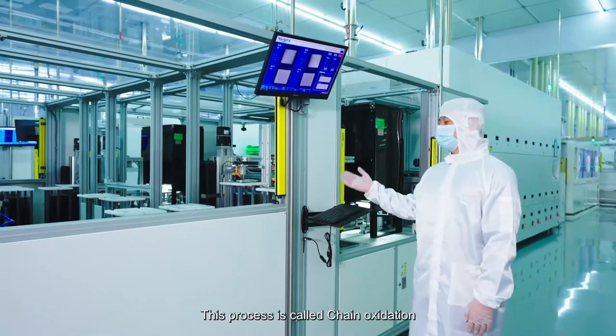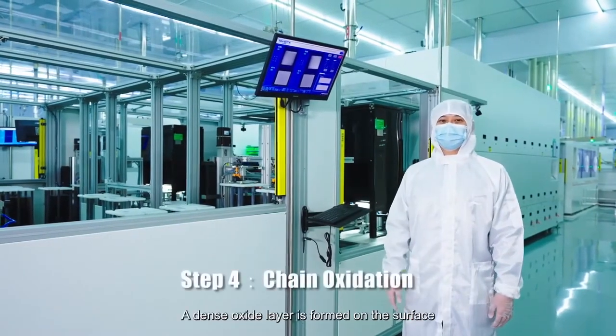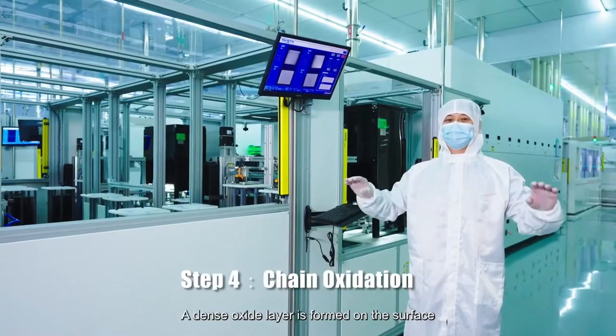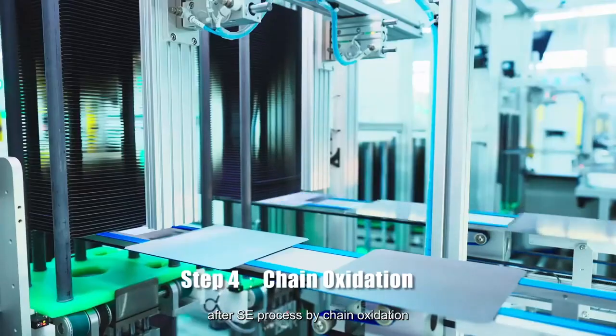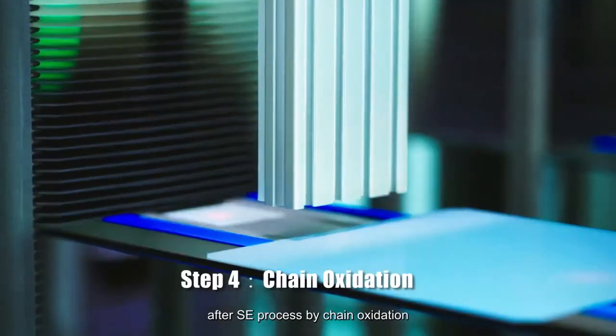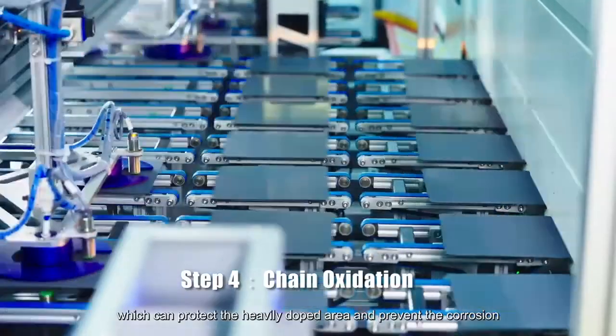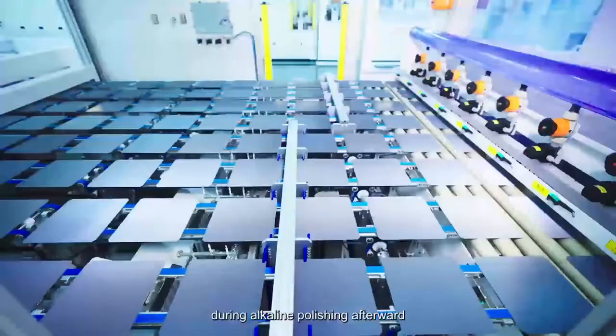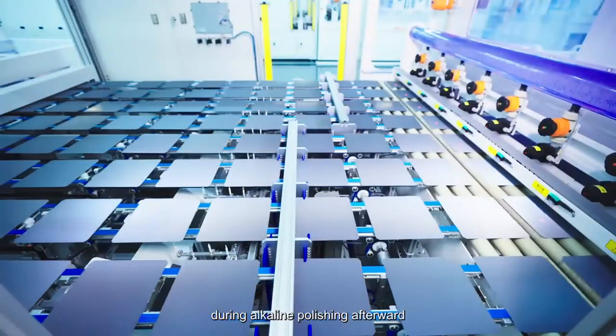This process is called chain oxidation. A dense oxide layer is formed on the surface after the SE process by chain oxidation, which can protect the heavily doped area and prevent corrosion during alkali polishing afterward.